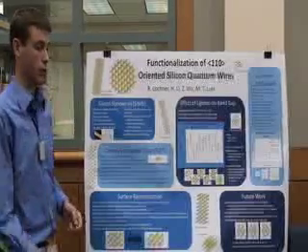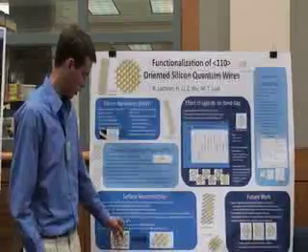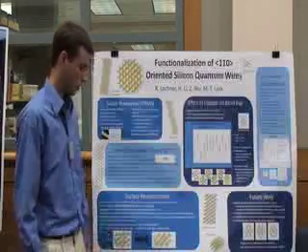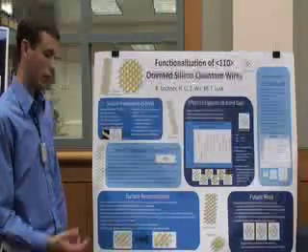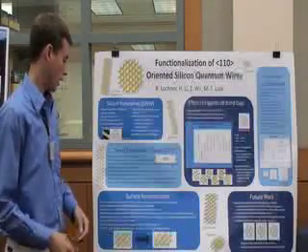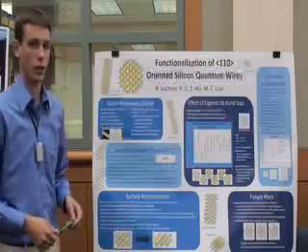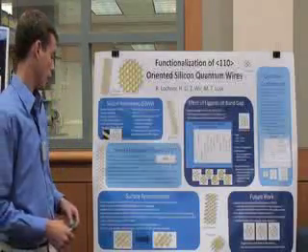Another thing I researched this summer was surface reconstruction. The silicon nanowire with the 110 orientation has on one side a plane or surface facet of 001, and that, on planar silicon or on the wire, originally has dihydride structure, so it has 2 hydrogens or 2 ligands per surface silicon.